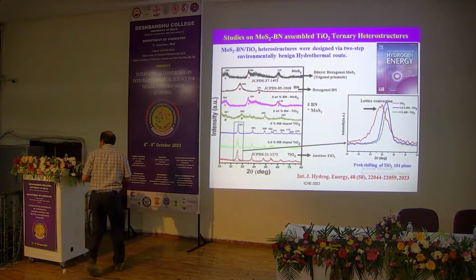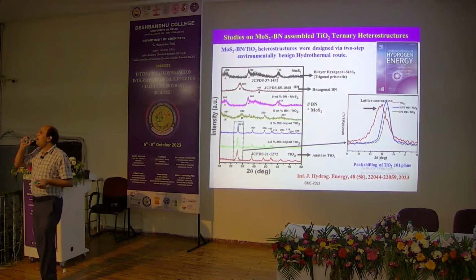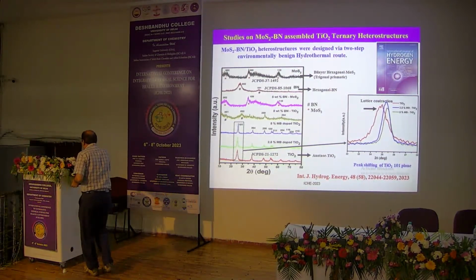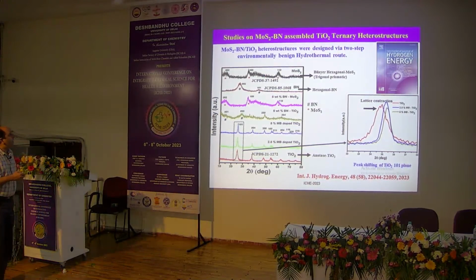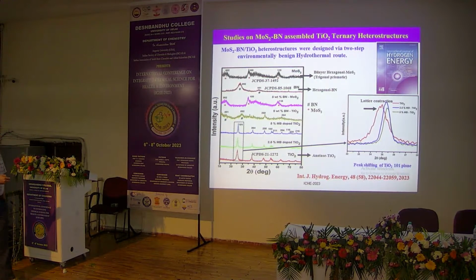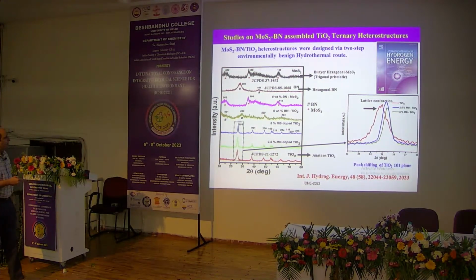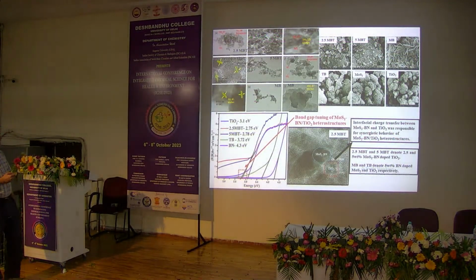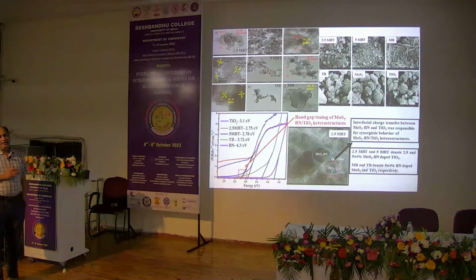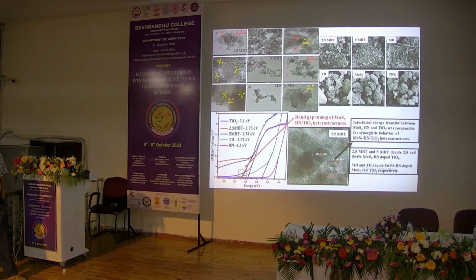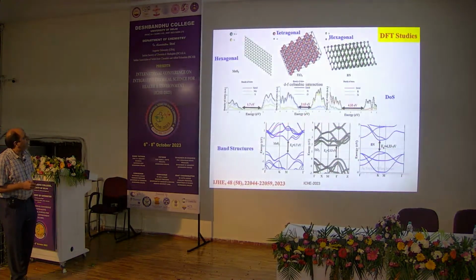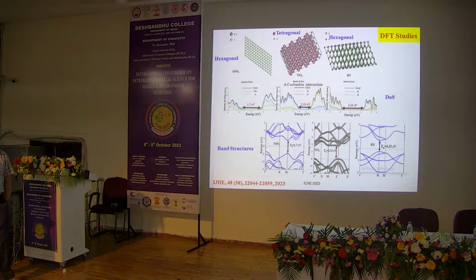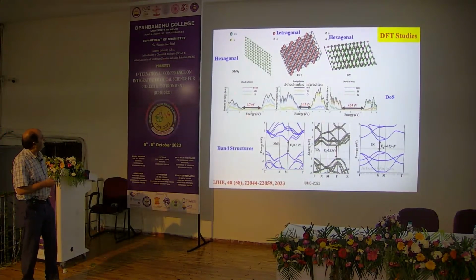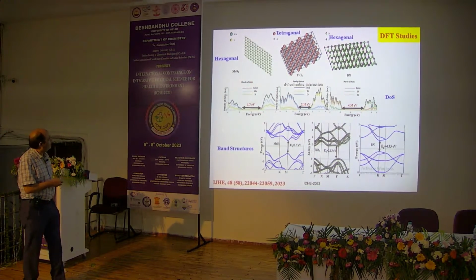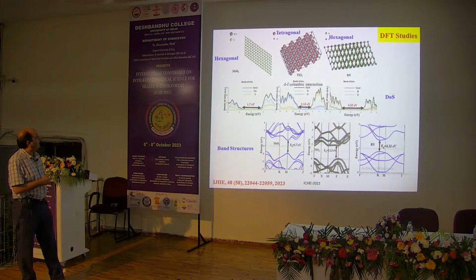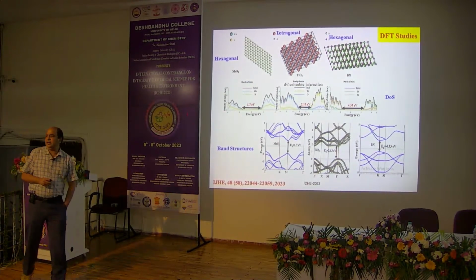Now coming to this ternary heterostructure, so these are the ternary heterostructures that we have prepared for molybdenum sulfide, boron nitride with TiO2. And these are the X-ray diffraction investigations. These are the detailed electron microscopic studies for the binary and the ternary heterostructures of the MoS2, boron nitride and the TiO2. And these are the DFT studies which show that the structure of MoS2 and boron nitride was similar, as well as the band gap, as observed by using the X-ray diffraction and the optical band gap studies.